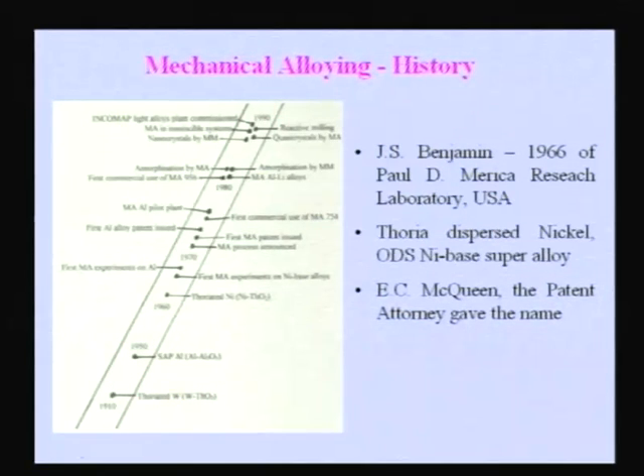temperatures. And when they were putting these yttria particles into the nickel based superalloys, they found that the wettability is very poor. So in order to improve the wettability, they thought they could coat it with nickel. The way to coat it, they thought, could be a ball milling technique, where ball milling has been used for quite some time. Even in metallurgy, we know that most of the ores, once we take them out from the earth's crust, we break them using a ball mill to make them finer sizes, so that they can be loaded into a blast furnace or something like that, any furnace.